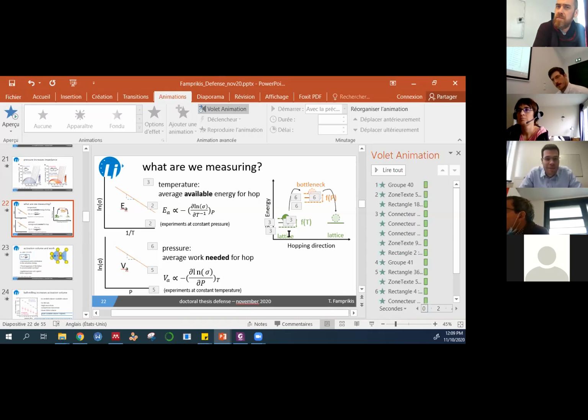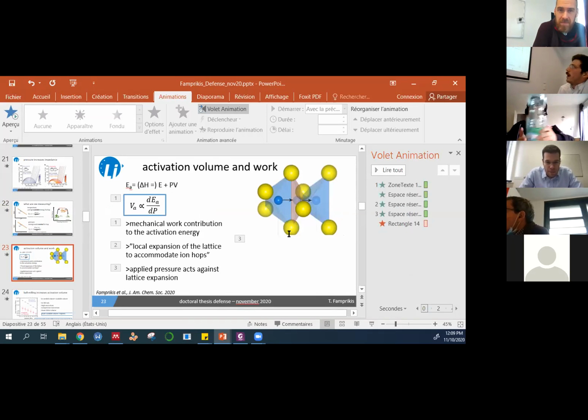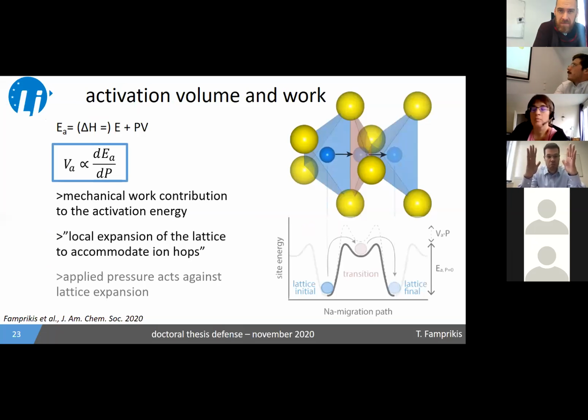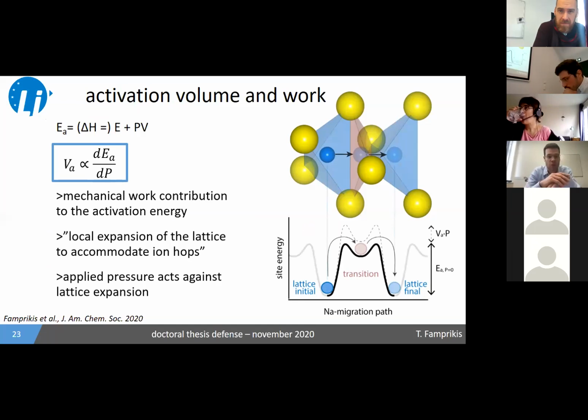This activation volume is something that bothers me in many ways in an understanding, and it's just that I think we really don't understand what the activation volume is. The way you draw it schematically is purely based on the idea that it changes the transition state and that this is only related to the transition state. Now, if you derive it, you have an isothermal compressibility in there, which would also mean that at higher pressures, you're sort of squeezing your atoms as well. And we know that structures, and especially locally, coordinations can change under pressure. Why are you saying this is only related to the transition state and not also the initial state?